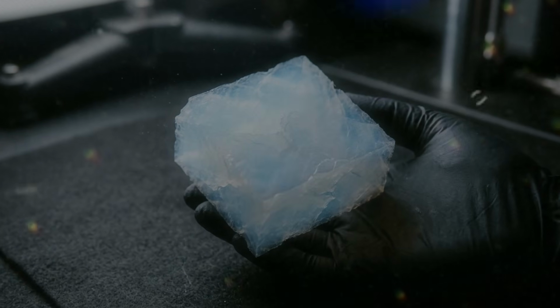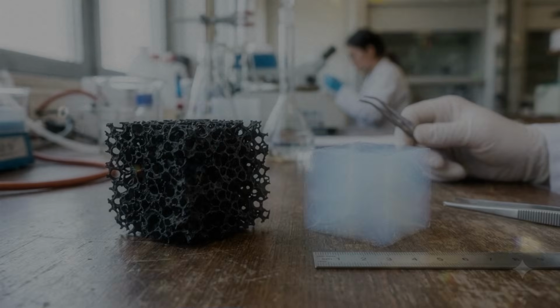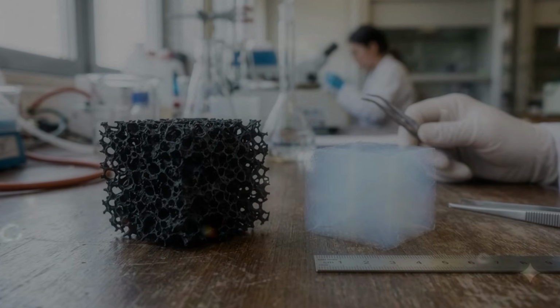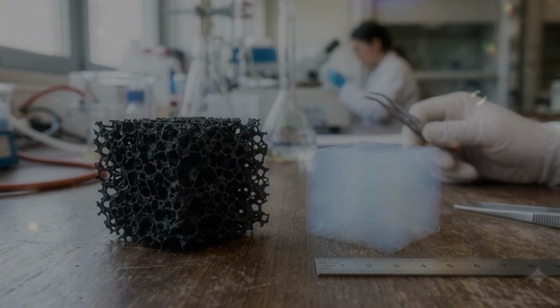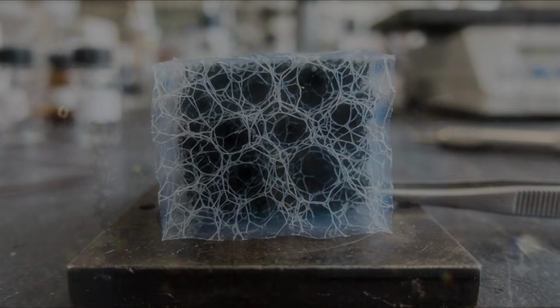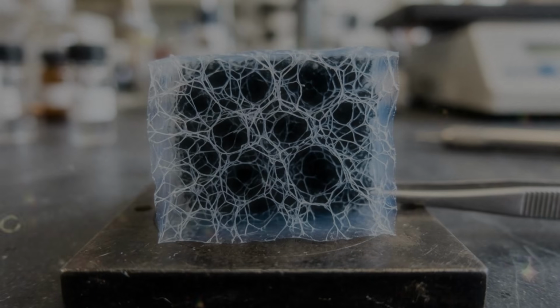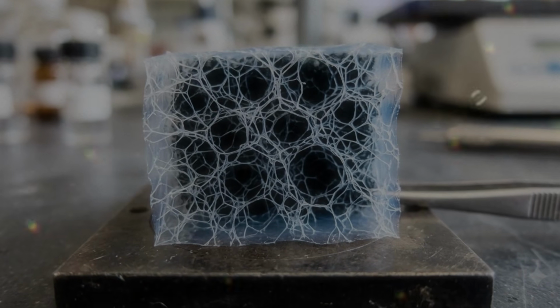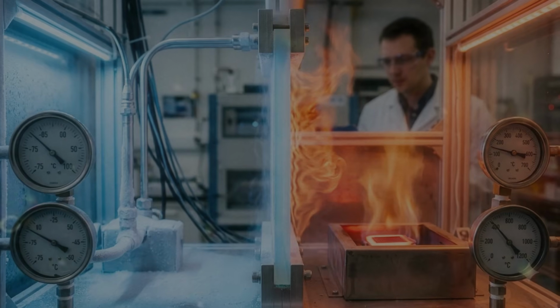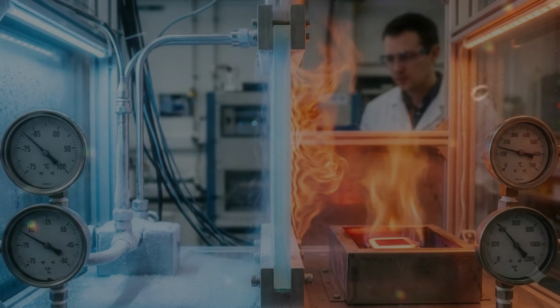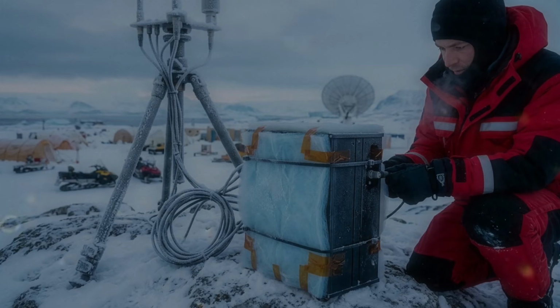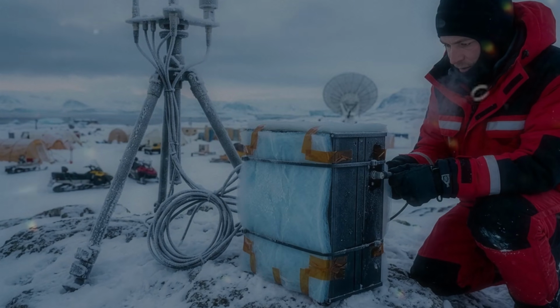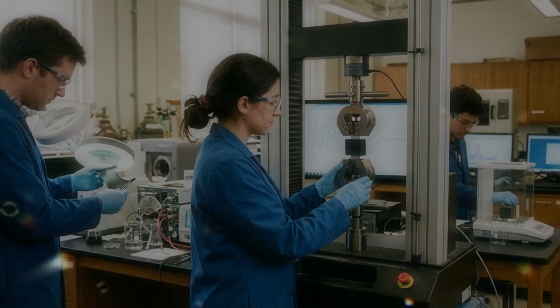Two sheets pressed flat against each other can exchange electrical charge more easily than two sheets touching only at their edges. Chemical bonds can create strong connections. Weak attraction can create contacts that separate when the material moves. Compression often changes these contacts. As the pores collapse, more sheets touch. Electrical resistance may fall. When the material expands again, some contacts disappear and the resistance rises. A sensor can use this change to detect pressure.